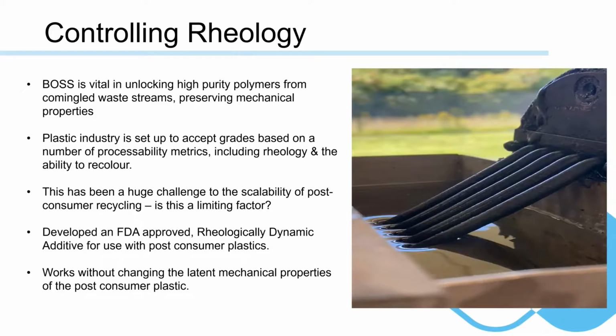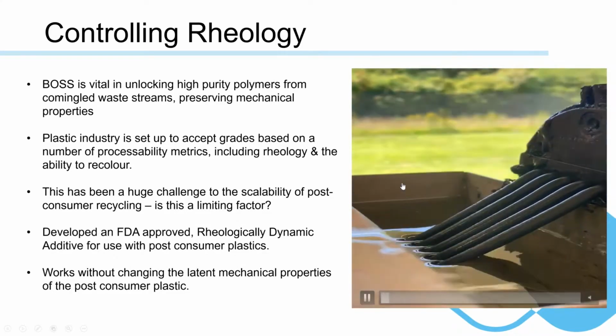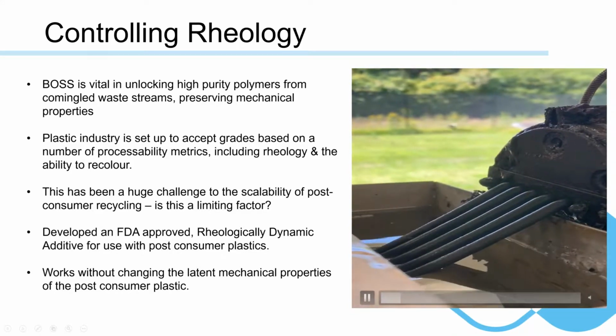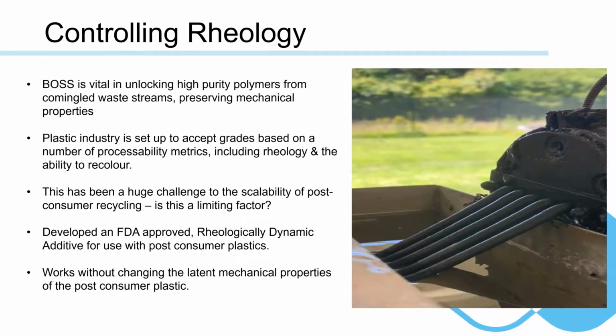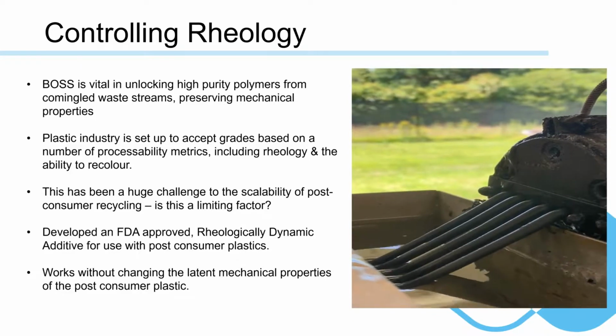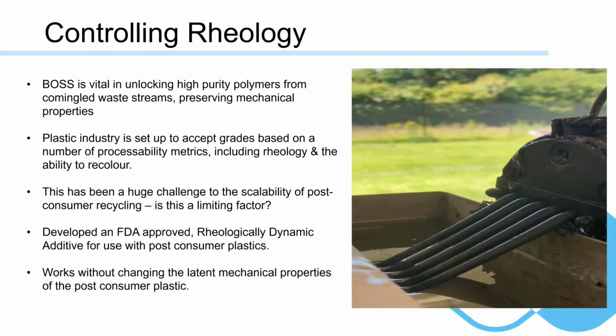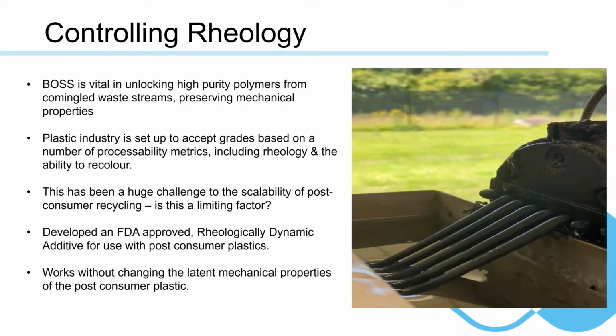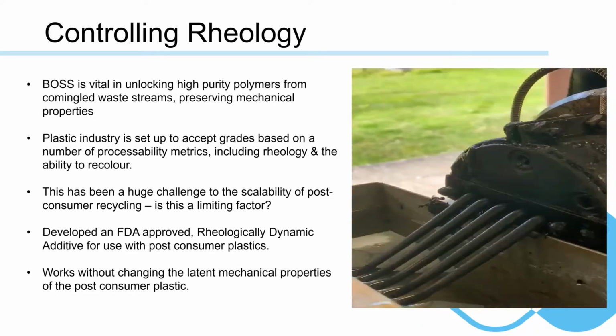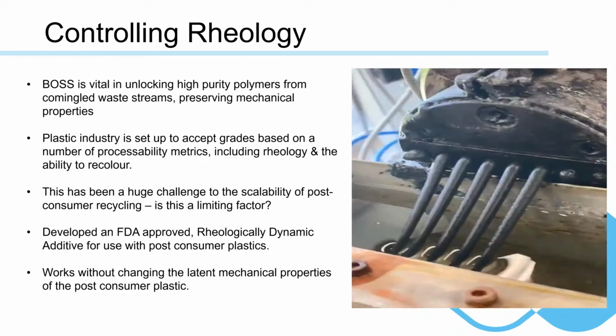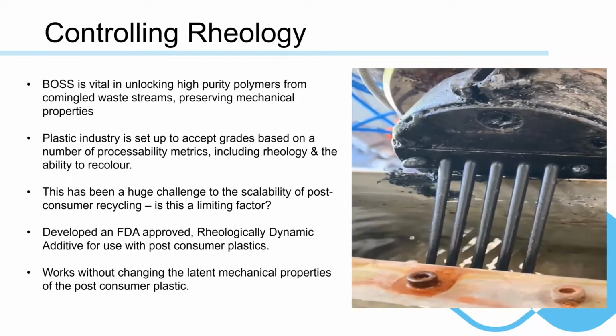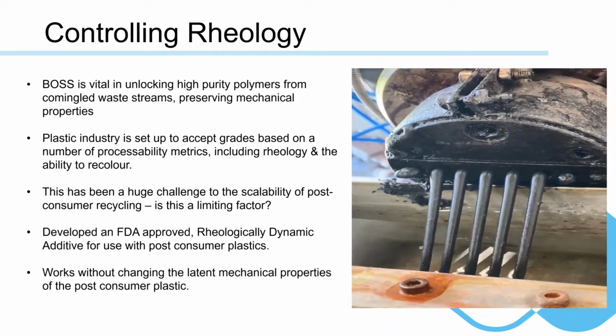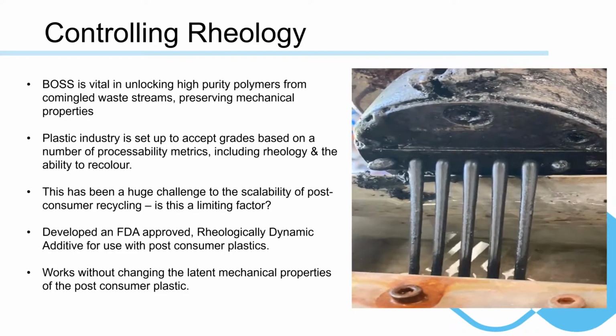A big part of what we then did to shore up our business model was look at ways that we could control the rheology. So I'll just play this whilst I talk over. Our material is a mix of molecular weights. Each strand you see there should actually flow at its own rate. So you should see some strands being much thicker than the other, some being quite thin and snapping. And this is a real challenge because the plastic industry itself is set up to accept grades based upon a number of processability metrics, including the rheology and the ability to recolor.